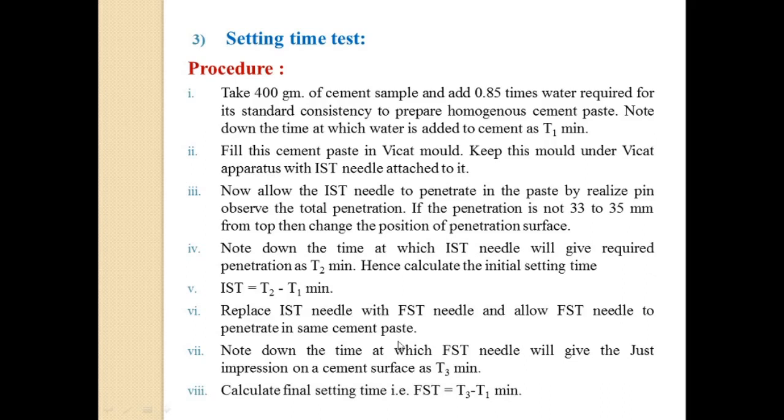And we know the initial setting time should not be less than 30 minutes and the final setting time should not be greater than 600 minutes, that is 10 hours. So that is all about the initial setting time and final setting time test.